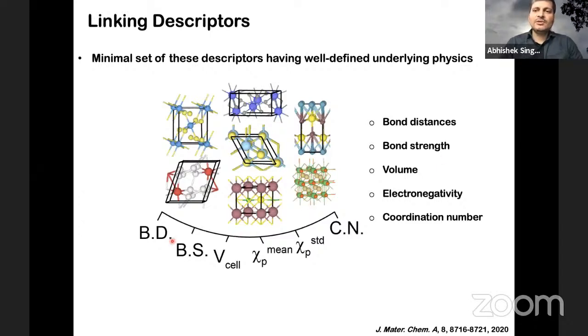They were very simple, like bond distance, bond strength, volume, electronegativity, coordination number. And you see that they are all kind of correlated and they do make sense. For example, bond distance, right? If something has a smaller bond, it will have a more dispersive band. That means its electronic transport will be governed by that, right? And similarly, if bond distances are smaller, the force constants are going to be stronger or more harmonic. And if you have a more harmonic system, the thermal conductivity will be high.